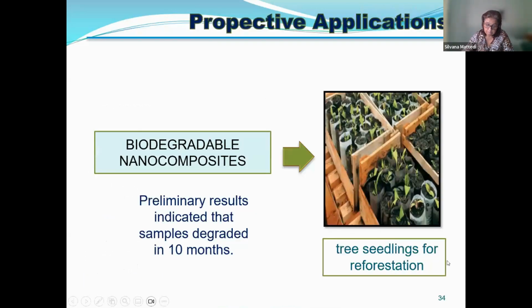But the thing is, they have the same mechanical properties. All three materials could be used as nanocomposite, for example, for tree seedlings in reforestation, because what we want is that after a while, the material disappears into the land and does not continue to be there. So they are biodegradable, and our preliminary tests show that they degraded in 10 months. So we can use this material to contain the seedlings for trees.